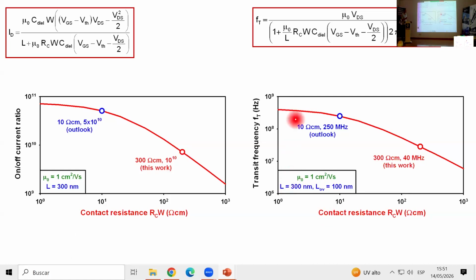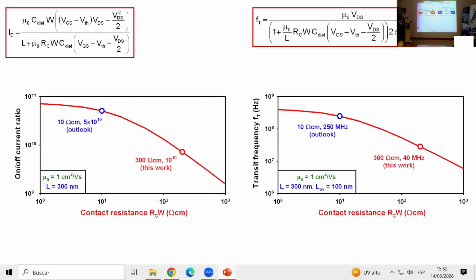But it gets even better in terms of transit frequency. Similar exercise here. So we're currently here at a contact resistance of 300 ohm centimeter and a transit frequency of 40 megahertz. And again, if we were able to bring down the contact resistance by an order of magnitude, something like 10 ohm centimeter, we could expect transit frequencies on the order of 200 megahertz. So there are two big incentives to continue working on reducing the contact resistance. And in my personal opinion, this parasitic contact resistance at the interface between the metal contacts and the organic semiconductor layer is currently the biggest impediment for making further improvements in both on-off current ratio and transit frequency.